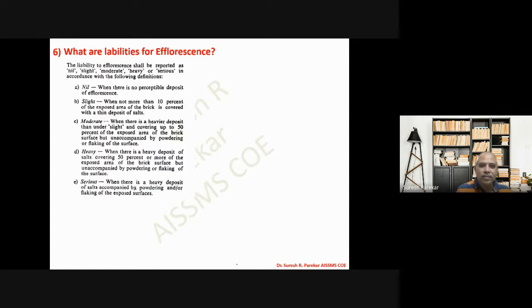What are the liabilities of the bricks, and that are given nil when there is no perceptible deposit of efflorescence. Efflorescence, we have soluble salts on bricks. So that white we have on these bricks, that white we are going to say is a deposit of efflorescence. Then nil when there is no perceptible deposit, slight when not more than 10% of the exposed area of the brick is covered with a thin deposit of salts.